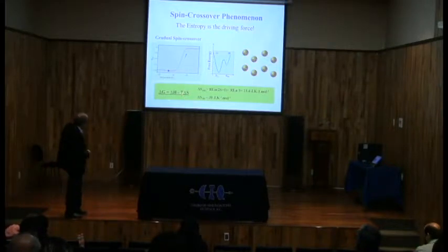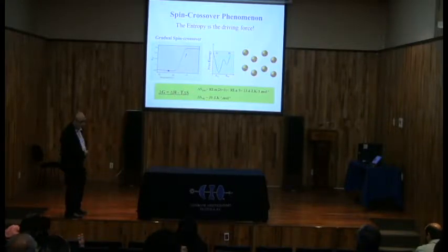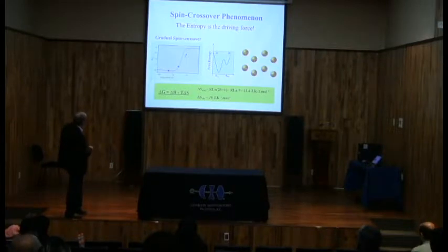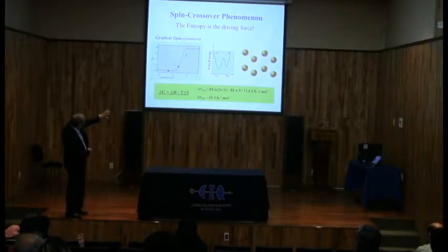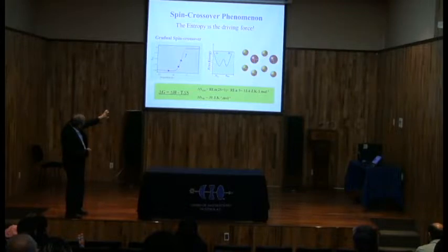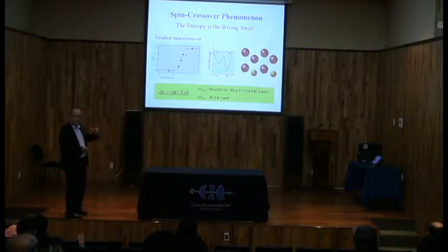If you change the temperature, for example if you increase it, you increase this part, so you will destabilize the system. If you heat your system, you will see in the double potential that you destabilize the low spin state towards the high spin form, and then you switch the system. If you continue heating, you keep destabilizing the double potential until the total conversion. Of course, the system is reversible.